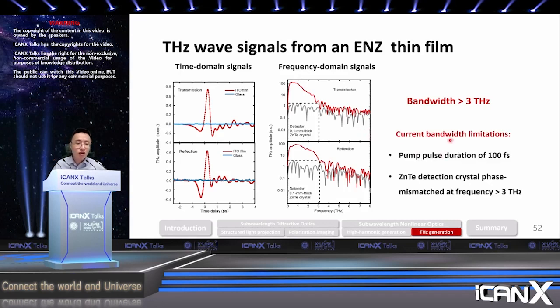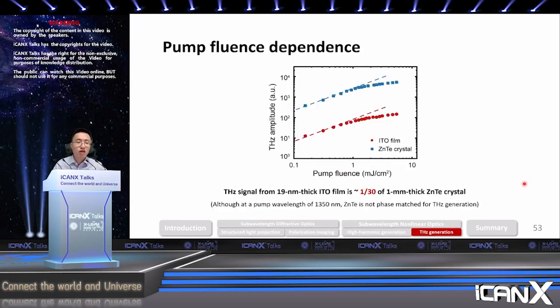Right now, we think there are two bandwidth limitations. The first one is that our pump laser has a pulse duration of roughly 100 femtoseconds. Another is that for our electro-optical sampling setup, we are still using a zinc telluride crystal that has a phase mismatch at frequencies greater than 3 terahertz. In the future, we expect there is no fundamental limitation in terms of the bandwidth of our device.